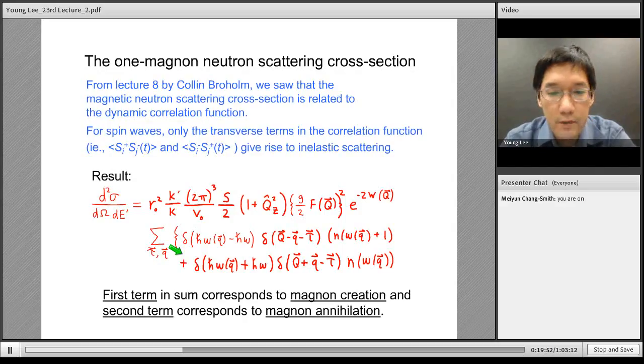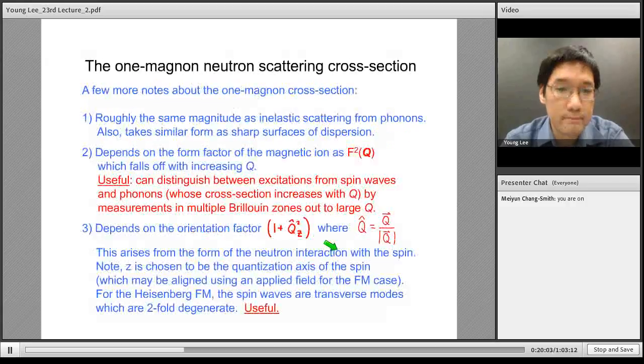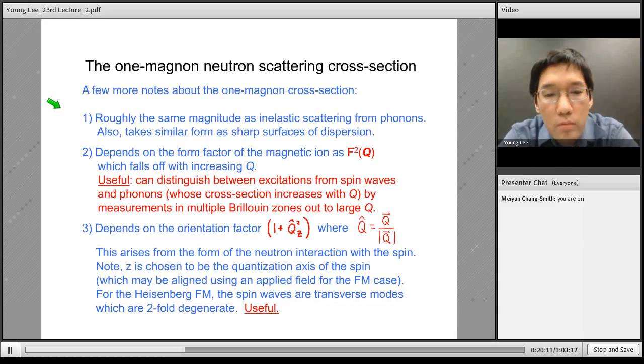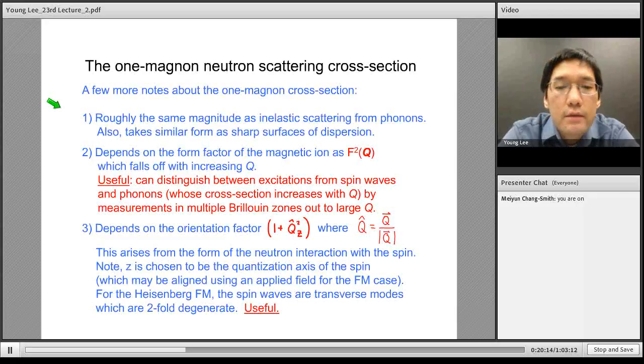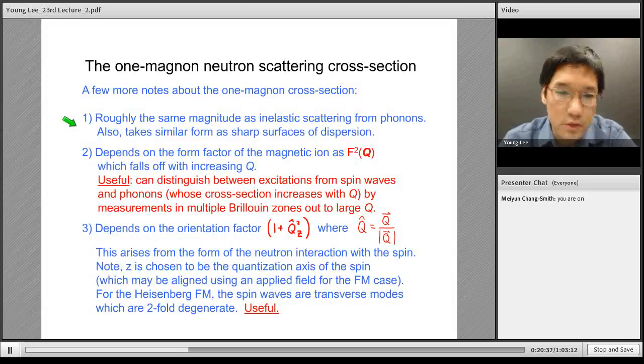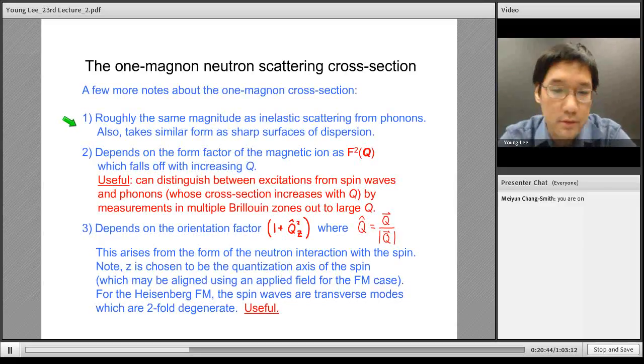And the different thermal factors here correspond to having detailed balance for those two types of excitations. So let me make a few notes about the cross-sections. One thing, the magnitudes are roughly on the same order as inelastic scattering from phonons. So when you see some excitations in a neutron scattering experiment, you might have to do some work to differentiate them to figure out if one's magnetic or from a phonon. And since these are well-defined excitations from an ordered state, they will have sharp surfaces of dispersion, and we saw that we had these delta function-like excitations.